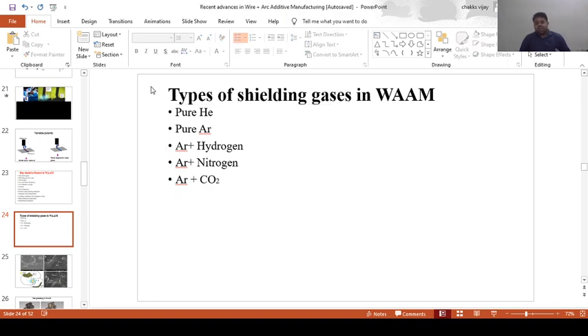How much hydrogen can we use? Generally we can go for 1 to 5% of hydrogen along with argon. Argon will be 95% and hydrogen will be within the range of 1 to 5. Then nitrogen also would be at the same level, and even CO2 also at the same level. So what is the use of hydrogen?